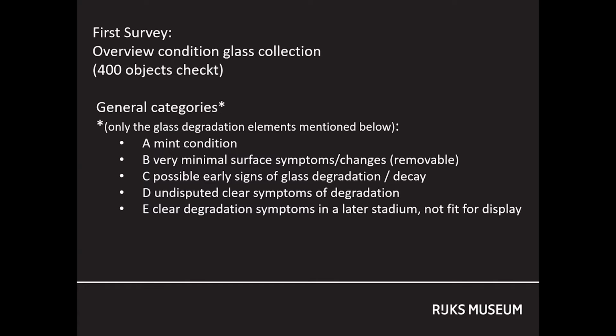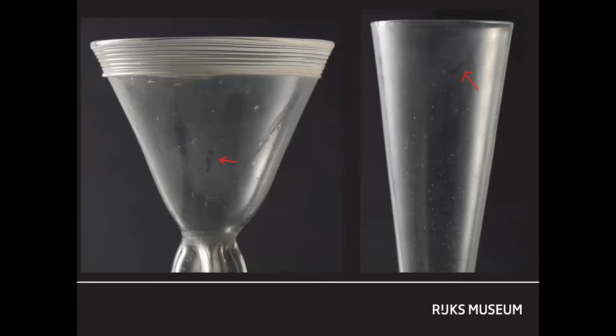On the slide, you see in very short terms the elements for degradation that were mentioned within this survey. After this survey, the objects were supposed to be cleaned and stored. Next slide, please. However, the outcome of the survey showed us that even within this core collection, there was a considerable amount of objects that showed signs and symptoms we could not clearly determine because they were unclear or faint and sometimes only be seen under raking light, and even then were hard to determine what it was that was seen.